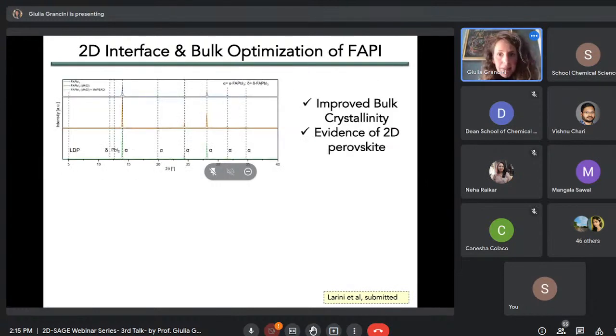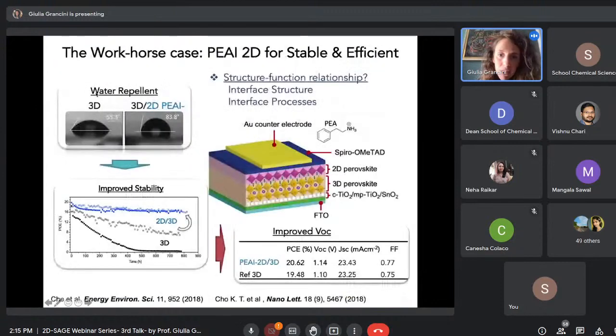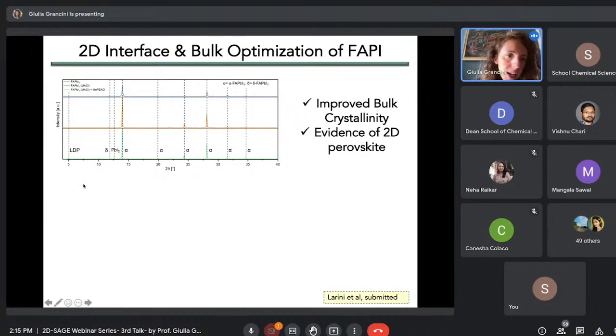following the strategy of 3D-2D bilayers. So first of all, it's important to characterize the bulk material, and you see from XRD that you do have evidence of the formation of a stable perovskite phase, the alpha phase. But when you use this phenylethylammonium-based cation, which is this one, to form the 2D perovskites, you do have also another peak at lower angles, which are indicative of presence of the growth of this thin layer of 2D perovskites.